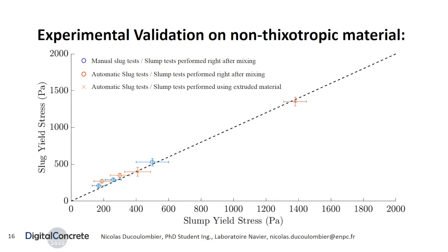Finally, the slug yield stresses are plotted against the slump yield stresses. One can notice the great fit for both automatic and manual slug tests with slump tests, meaning that the slug tests give reasonably good estimation of the yield stress at the nozzle level. An interesting discussion concerns the validity of the assumption that the mortar at the nozzle is a pure plastic material. In reality, the analysis proposed by Coussot and Gaulard suggests that this assumption would lead to an overestimation of the yield stress when the viscosity cannot be neglected, meaning for small values of yield stress. This is in qualitative agreement with the present graph. Simple ways to take into account viscosity could be imagined and will be studied in future work.